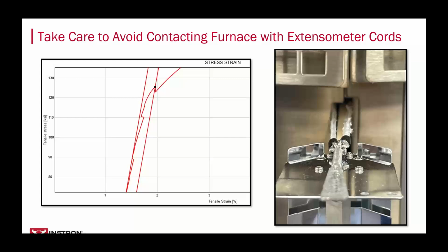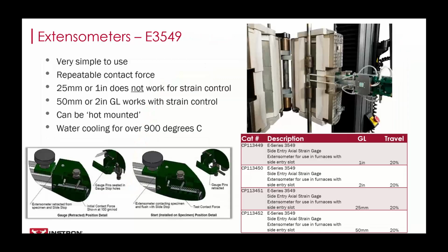or if you want to get the most benefit from your high efficiency furnace, you can, of course, upgrade to a hot mountable one. Hot mounted extensometers are supported by a rigid structure outside of the load string. So you remove the need for nylon cords and can take full advantage of the narrow side entry ports in modern efficient furnaces. One of the most common hot mounted extensometers we see is this one here, the E3549.